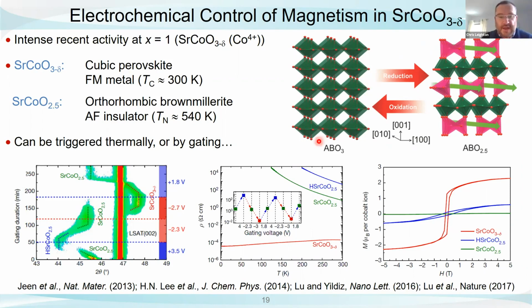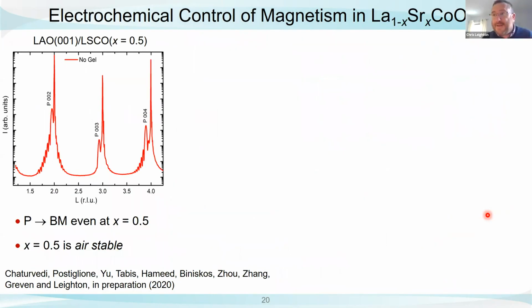This has now been shown in these papers that I highlight here. So it's been shown by operando X-ray diffraction, for instance, that we can go between Brownmillerite and perovskite. One of these things is an insulator. The other one is really a metal. One is ferromagnetic, and the other one is an antiferromagnetic insulator. What we have shown recently is that we can also do this even at x equals 0.5. And that's actually quite important because unlike at x equals 1, at x equals 0.5, these materials are air stable in both forms. The perovskite and the Brownmillerite are both air stable.